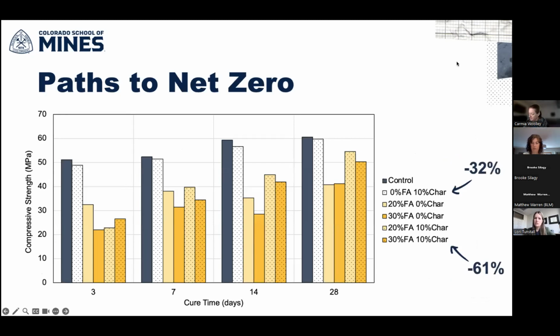We have done some analysis with biochar and fly ash. So if you look at this plot, I'll just give a brief overview of how to interpret this. The gray is the control. All of the bars here with the dots are mixes that include biochar, 10% biochar replacement of the cement. And then the light yellow is with 20% fly ash, also replacing the cement. And then the gold color is 30% fly ash. So if we look from left to right, focusing on this 28-day strength, we can see with the biochar, we've got something comparable to the control when we just have the biochar.